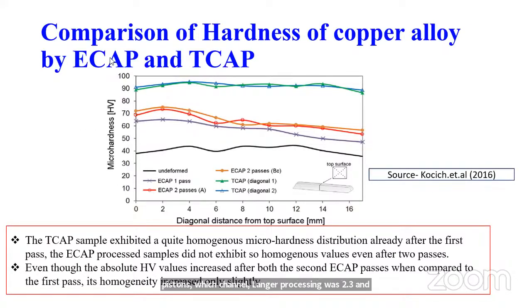You can see the comparison of hardness of the copper alloy processed by ECAP and TCAP process. These are the ECAP processed samples. This is the undeformed sample where the microhardness is in the range of 40. And ECAP 1 pass, it increases to 60, and ECAP 2 passes increases to 70. But you can see the TCAP processed samples, these two, green and blue color, have higher hardness when compared to the ECAP processed samples. So it shows clearly that inducing more deformation zones increases the hardness and strength of the material.